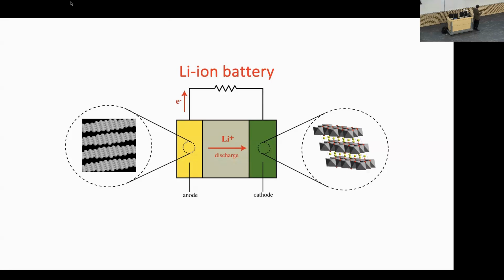In this image right here, this is a transition metal oxide where the corner points are oxygen, and the center of these octahedra are all transition metal, like cobalt or manganese or nickel. They form these layered sheets, like these 2D layered materials. And between these sheets is where the lithium likes to intercalate. They really like this crystal structure.